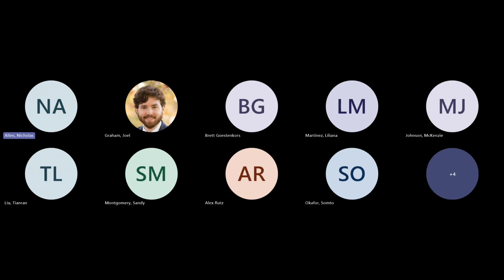So what we wanted to do within this collaboration was use the granular hydrogel and the 3D printability to form precise bio-encapsulating electrodes around specific points of the antenna and measure how the local field potential amplitude across the antenna responds to different concentrations at those locations. So first, towards this goal, we wanted to look at, can this material perform in a basic electroantennogram setup? Can we encapsulate the ends of the antennas, interface those ends with sensing electrodes, connect those electrodes to our data acquisition system, apply odor, and be able to record signals generated as a result of those odors?